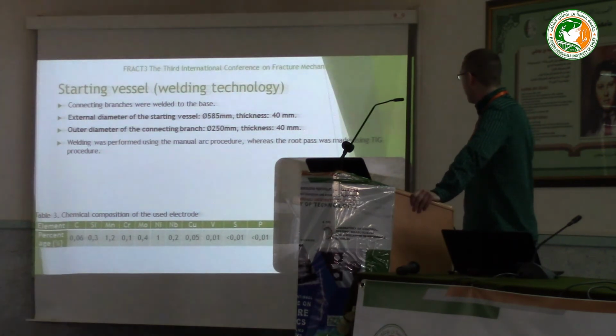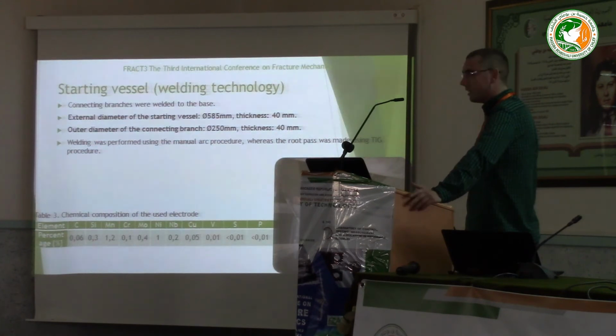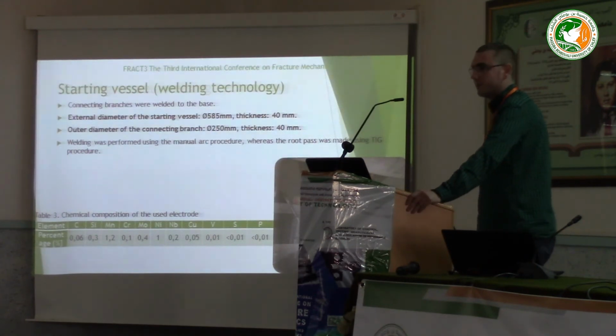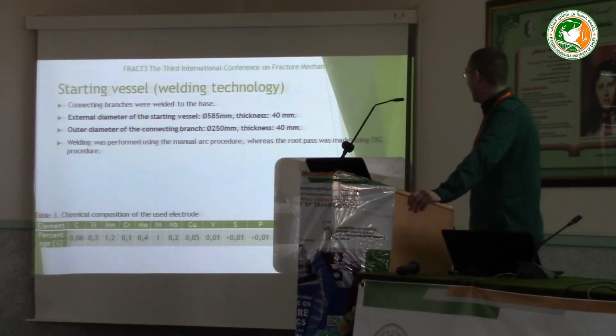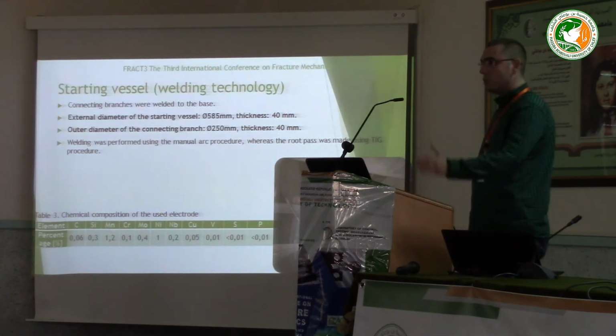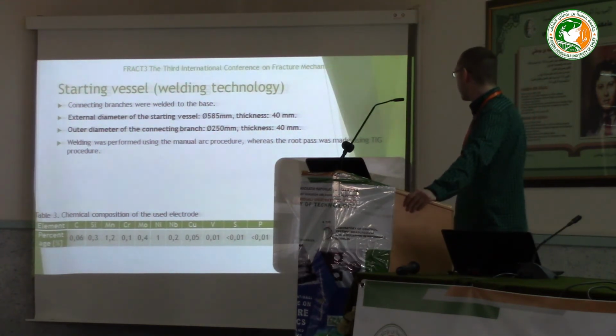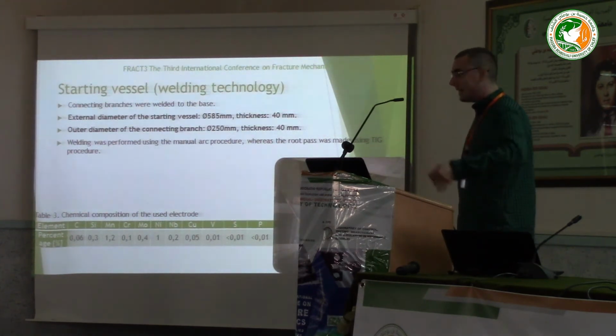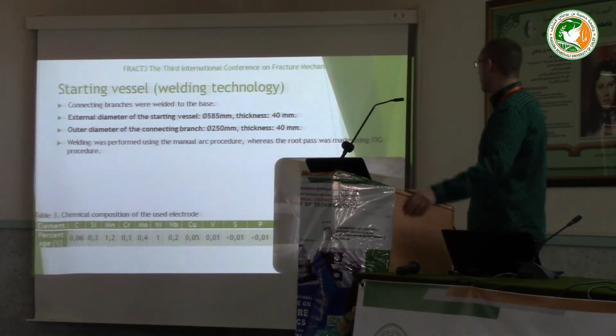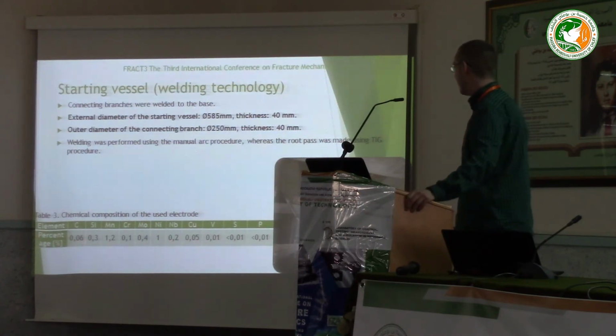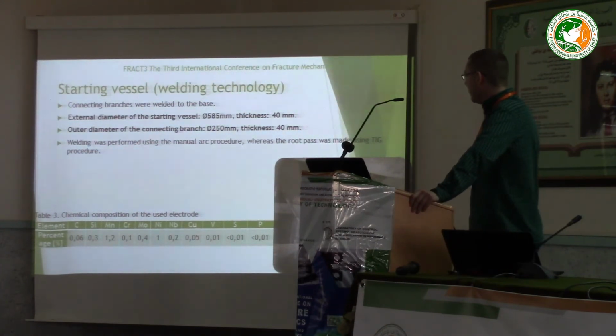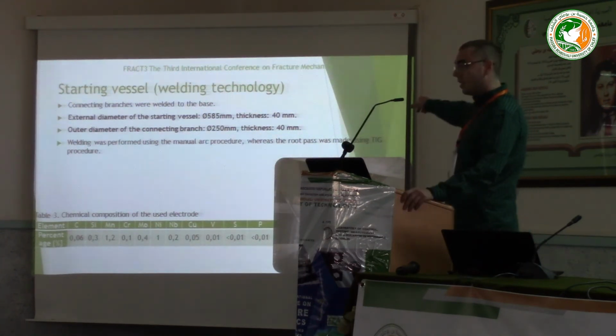This starting vessel was manufactured 25 years ago. So the welding technology and welding procedure were performed 25 years ago. Welding was performed using the manual arc welding procedure, and the root pass was made using the TIG procedure with a tungsten electrode. The chemical composition of the used electrodes you can see on the slide.